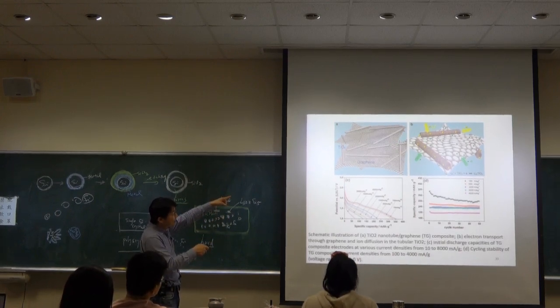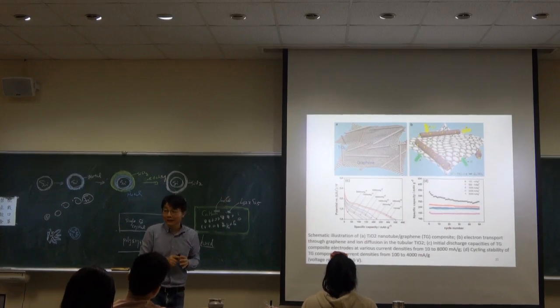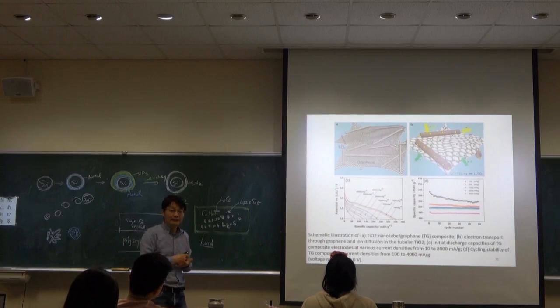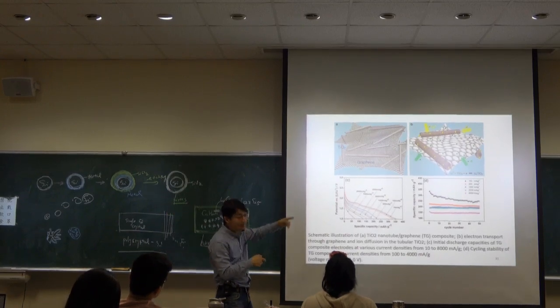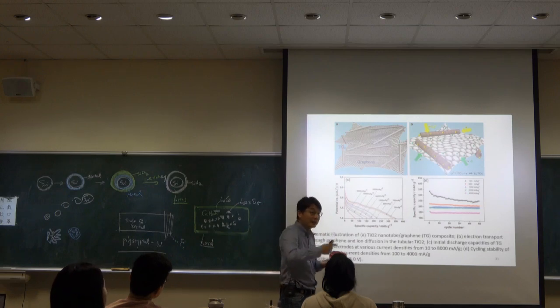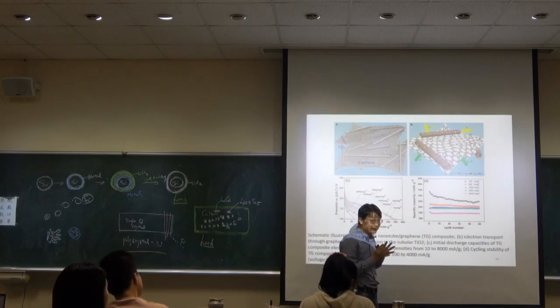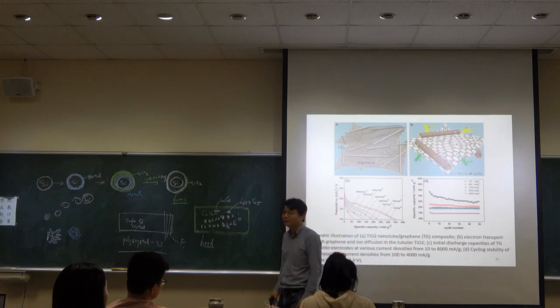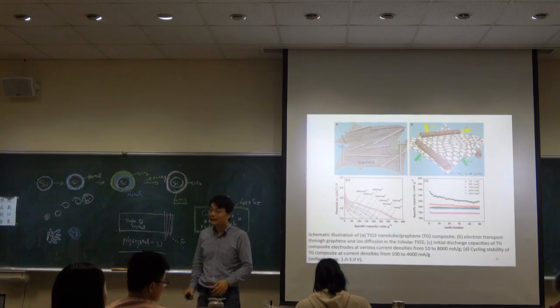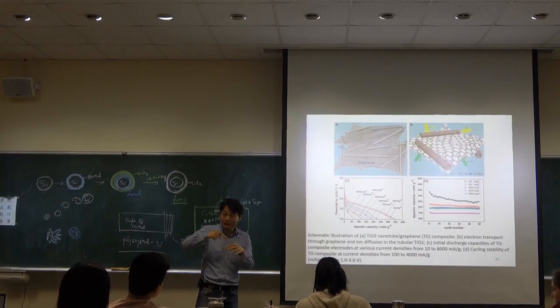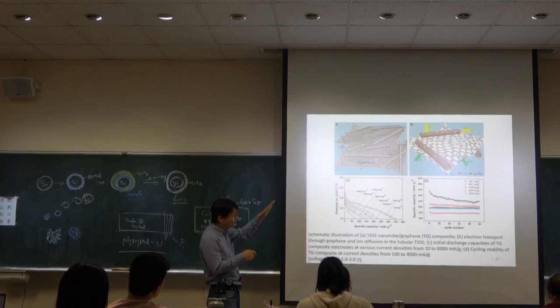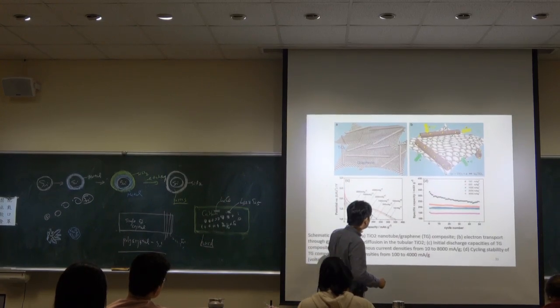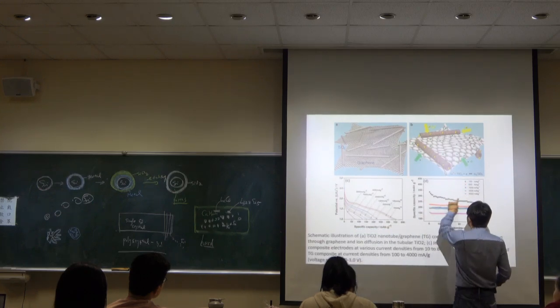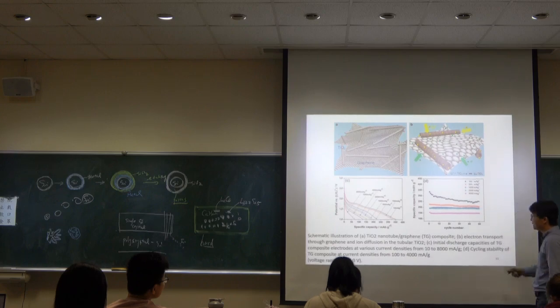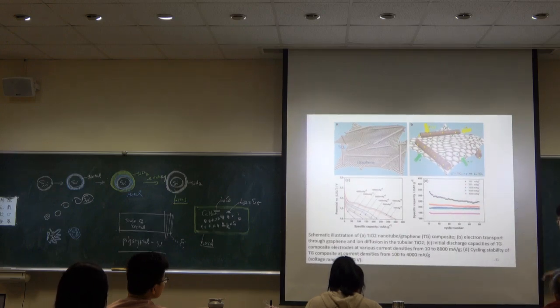In the previous slide, we talked about how titanium dioxide has poor ionic conductivity, right? The conductivity is poor. But you mix it with graphene, and graphene's conductivity is quite high. So graphene can support titanium dioxide in achieving high electron transfer, and TiO2 accommodates charge and discharge quite stably. So you can take advantage of both. You can see here the capacity is quite high, and this is the cycle. This is just some of the reference.